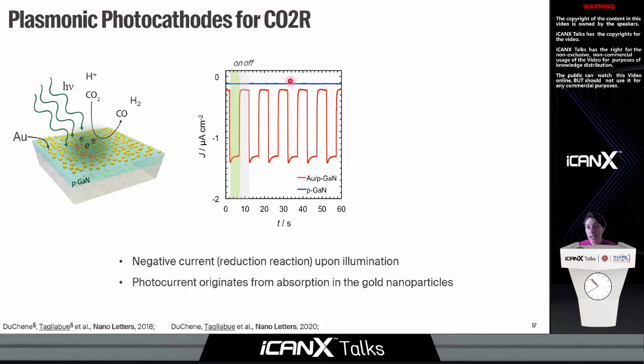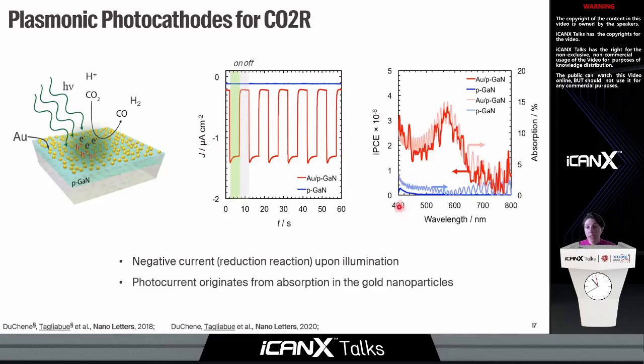And as you can see here, the semiconductor without the nanoparticles does not have any photocurrent. We also did this measurement as a function of the photon energy, and the solid red curve is the photocurrent generated, and the light red curve is the absorption spectrum of the gold nanoparticles. So as you can see here, all of the current that we are measuring is originating from the metal absorption, not from the semiconductor, which is different from a conventional photoelectrode system.